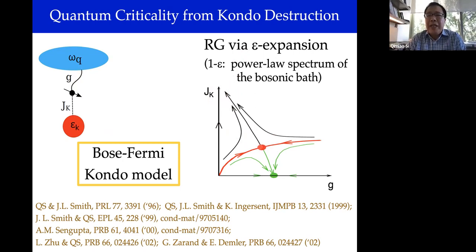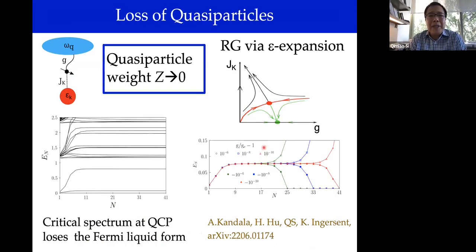And in the end, there's a possibility of reaching this red fixed point. This red fixed point is interesting because the black fixed point is where the Kondo singlet characterizes the ground state, and the weight of the Kondo singlet shows up in the weight of the quasi-particles. But if you reach this red fixed point, a number of different things happen, but the upshot is that the quasi-particle weight goes to zero, and in the lattice model, the quasi-particle weight will go to zero everywhere on the Fermi surface.